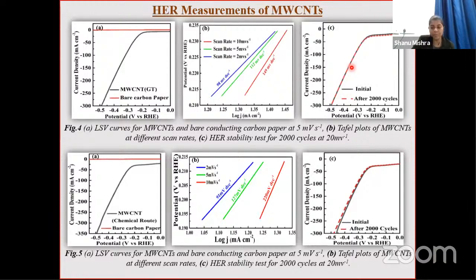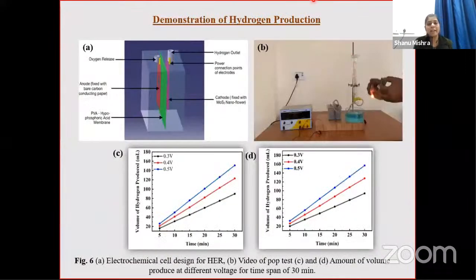So we have also designed an indigenous electrochemical cell, and in the cathode chamber we have used MWCNT coated conducting carbon paper of area 4 centimeters square as the working electrode. For the anodic chamber, we have used bare carbon paper, and for the separator, we have used the PVA H3PO4 membrane. We produced hydrogen and collected it by a downward displacement method. And this is the image of the full setup that we have designed.